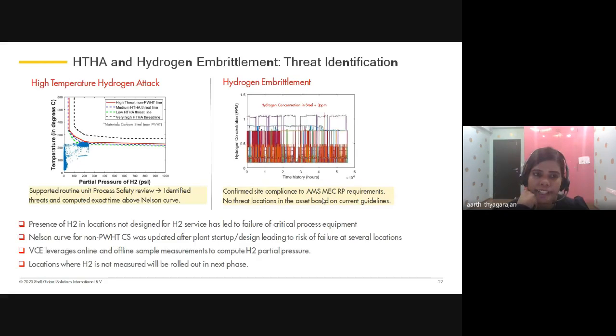Yeah, so this is a mechanism called HTHA in short. Otherwise, it's called high temperature hydrogen attack. It's a degradation of mechanical properties of steel by high temperature reaction of absorbed hydrogen. Please note it's the absorbed, which means it's a volumetric absorption, with carbon in the steel. Yeah, how they react with each other. So at elevated temperature, some of the molecular hydrogen in the process environment dissociates into atomic hydrogen, which can diffuse into the steel. Now, this HTHA, high temperature hydrogen attack of steel, can result in surface decarburization, internal decarburization, fissuring, and cracking.